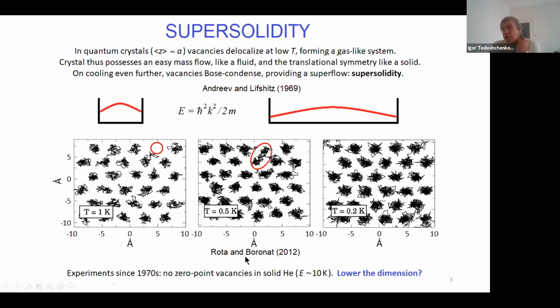In 2012, Rota and Boronat applied quantum Monte Carlo analysis to a two-dimensional system of helium atoms, helium-4 atoms in this case, where a vacancy was artificially introduced, so that the number of atoms was smaller by one than the possible sites. We see that at 1 Kelvin, the vacancy is very well localized. You can always point it out. At 0.5 Kelvin, it is already not so well localized. It's somewhere, here and here. And finally, at 0.2 Kelvin, you cannot say where it is at all. At each atomic site, there is a finite probability to find the vacancy, not the atom. So it's delocalized. This is a brilliant confirmation of the suggestion by Andreev and Lifshitz.